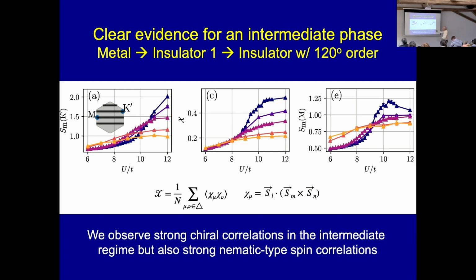What you see here is the growth of the chiral spin correlations as a function of U. So indeed, there is increasing chirality. This is the increase of the 120-degree order, which eventually wins at large U. But there is also a sort of intervening ordered state, which has nematic spin correlations that take place in between. And it's not totally clear whether this intermediate phase is a chiral spin liquid eventually, or whether it's a state in which there is both chirality and another type of magnetic order.